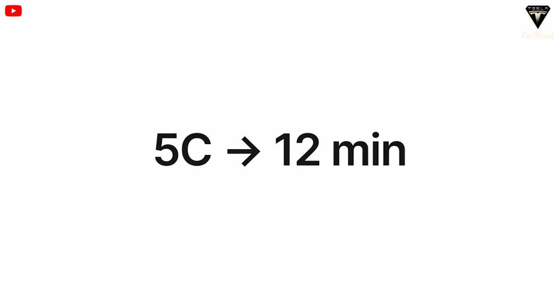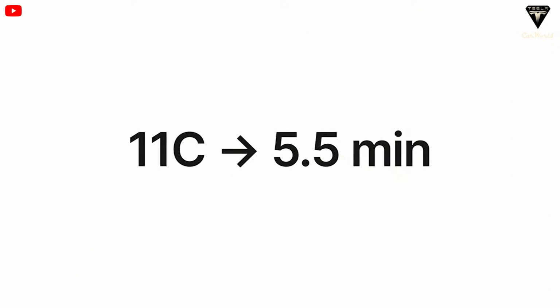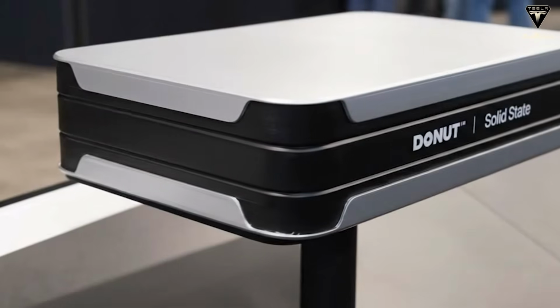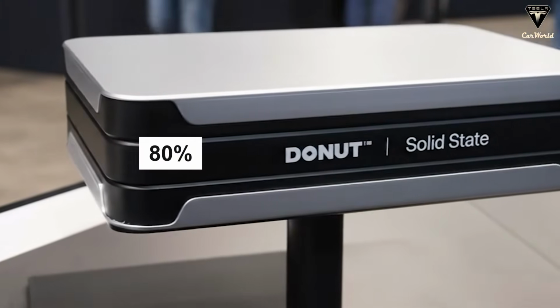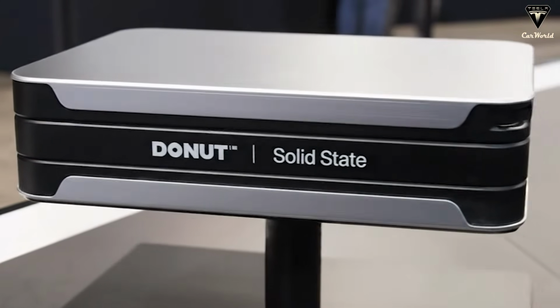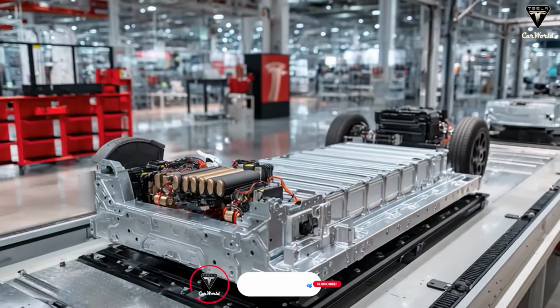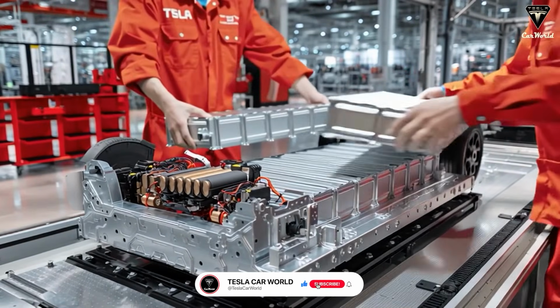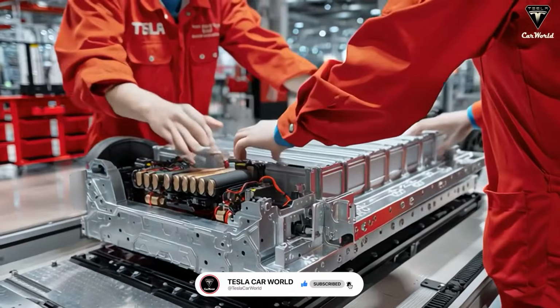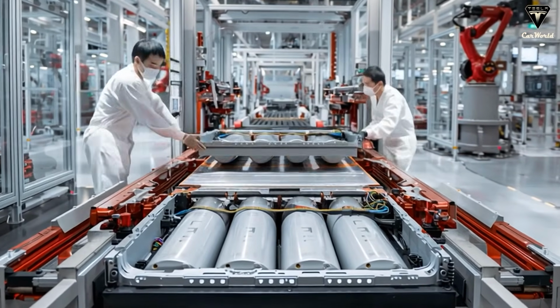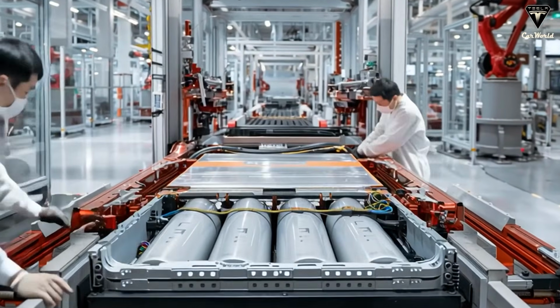First, Donut Lab is right. If you've watched their demonstration video of the charging speed, it is indeed impressive. Looking at the high C rates published by VTT, this battery is capable of handling charging currents of up to 11C, reaching a full charge in about 5 to 6 minutes, or even 4.5 minutes as some reputable analyses have reported. At a 5C charging rate, it can reach 80% in under 10 minutes. These are impressive figures, considering that conventional batteries typically operate at around 1C to 2C. Even the fastest lithium-ion EV batteries today, whether LFP or NMC, cannot exceed 6C under ideal conditions. An 11C rate is quite extreme.